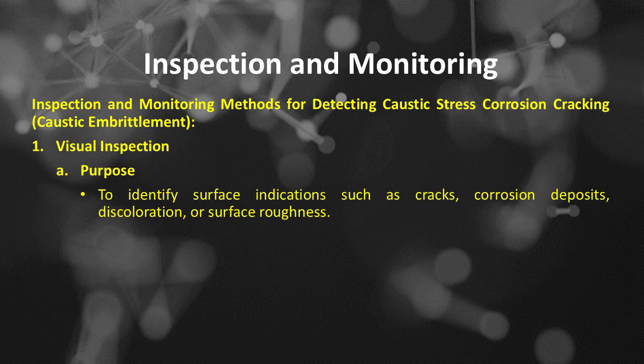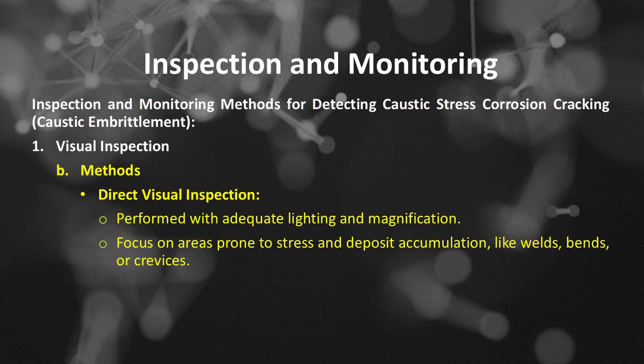Includes, number 1 is visual inspection. It is purposed to identify surface indications such as cracks, corrosion deposits, discoloration, or surface roughness. The first method in use for visual inspection is direct visual inspection, performed with adequate lighting and magnification. Focus on areas prone to stress and deposit accumulation, like welds, bends, or crevices.